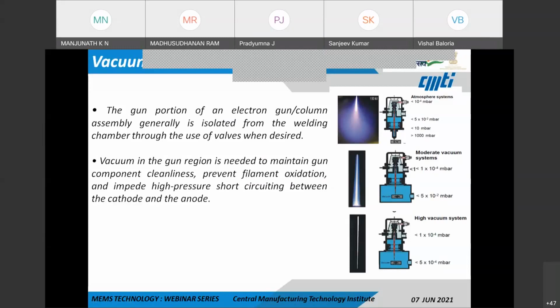So when I say the E-beam process will happen at a vacuum level, here is a classical example wherein we see that the gun is also maintained at a certain negative pressure, that is at vacuum 10 power minus 4 millibar, but the chamber is maintained at atmospheric pressure. So once the beam enters the chamber, there is a dispersion of this beam and the actual beam power is not being utilized by the workpiece.